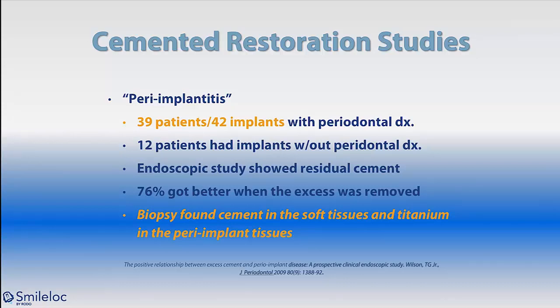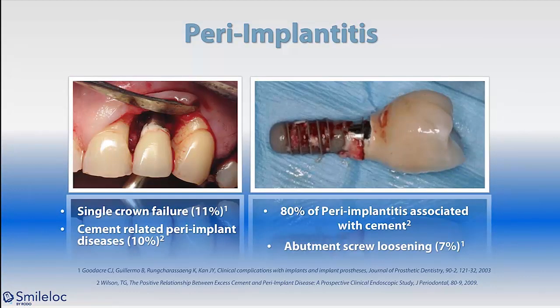The biopsies found cement in the soft tissues and titanium in the peri-implant tissues. So the cement was beginning to dissolve some of the titanium. We could see here, on the slide to the left, an anterior tooth with cement along the long axis of the implant. On the right, a posterior tooth, with cement along the long axis of the implant. Single crown failure, 11%, is because of peri-implantitis, according to the literature. Cement-related peri-implant disease is at least 10%, and 80% of implantitis is associated with cement.